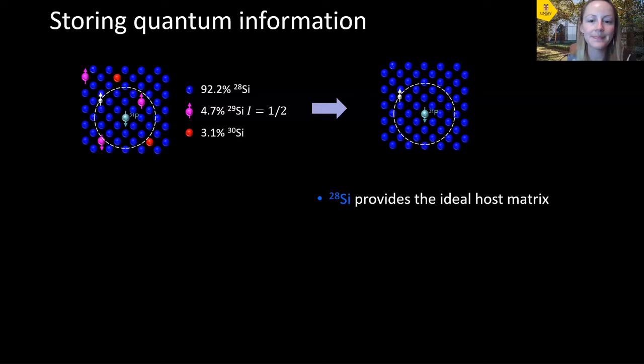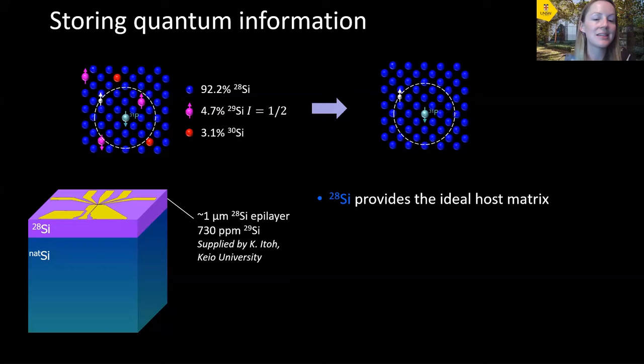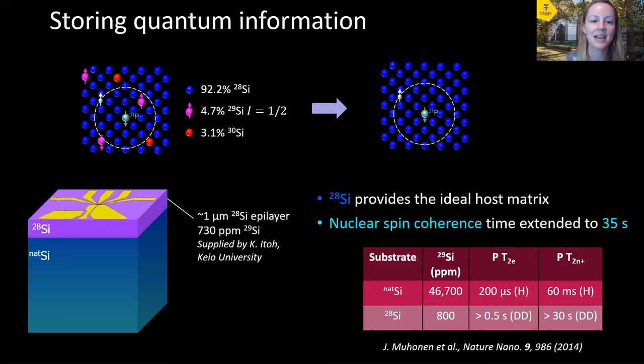So for our devices, we use an epi layer of deposited silicon 28 onto a natural silicon handle wafer. And inside this silicon 28 layer, that's where our donor qubits will live to have these low noise properties. And with this device, we've been able to drastically increase our coherence times. Shown here in the table is a comparison between the coherence times of your phosphorus donor electron and phosphorus donor nucleus for the natural silicon case, which is pretty short.